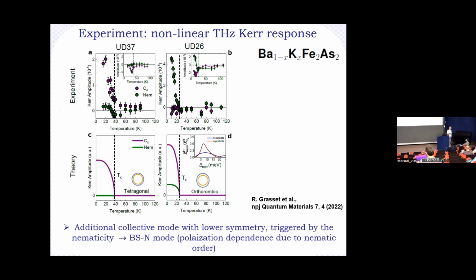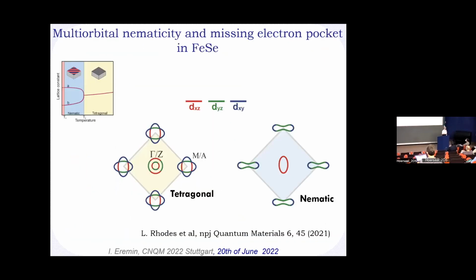Okay, so why is that interesting? First, let me tell you that something like this has been seen by the group of Yann Gallais, where they indeed found, in another example of an iron-based superconductor in the nematic state, the observation of another mode deep inside the superconducting state, whose polarization and angular dependence is not reflective of the pure Bardasis-Schrieffer mode, but rather of the nematic mode. Now, why would it be interesting to look into iron selenium?